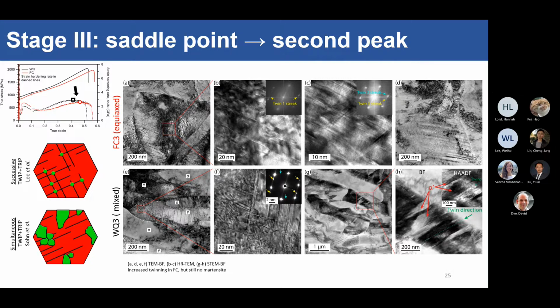So we raised the stacking fault energy a little bit more, adding a bit more carbon to get twins instead of epsilon martensite. What we've also noticed is that if you add a lot of carbon, and go beyond about 23 to 30 millijoules per meter squared stacking fault energy, then you transition from the successive TWIP plus TRIP into the simultaneous TWIP plus TRIP mode. So this is an observation. It hasn't actually been proven yet, but it is an interesting fact. It definitely needs a bit of research, but you do transition between the modes when your carbon content increases, and therefore your stacking fault energy, austenite stability, and so on. I cannot give you an answer why it does that, but it does.